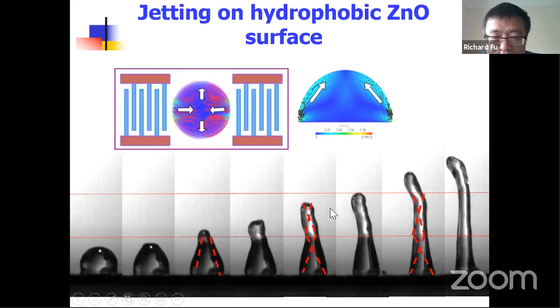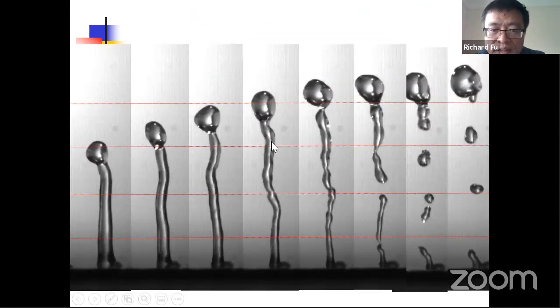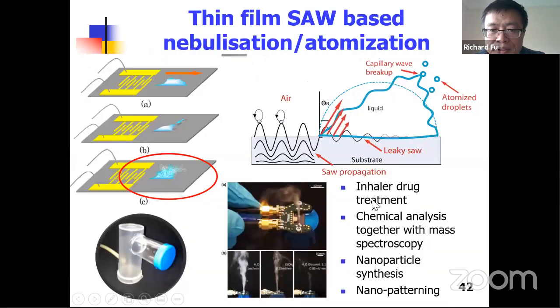So how to realize it? We have different options. We can use a circular IDT, which I will not show here, which concentrates the energy. Here we have an example, not circular, but two IDTs from both sides. The energy will propagate from both sides, dissipate into the droplet, and push it up. The wave energy is reflected by the liquid interface and pushes up again and again until the surface tension couldn't hold the elongation and the droplet breaks up into small droplets, which is good for printing purposes.